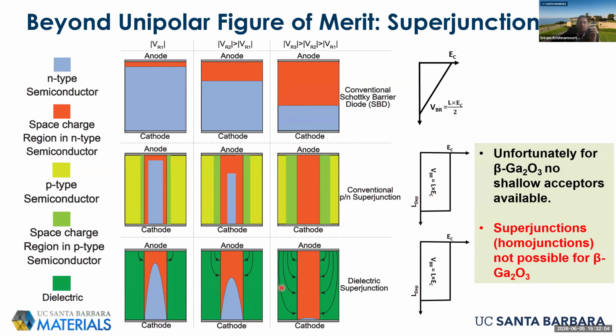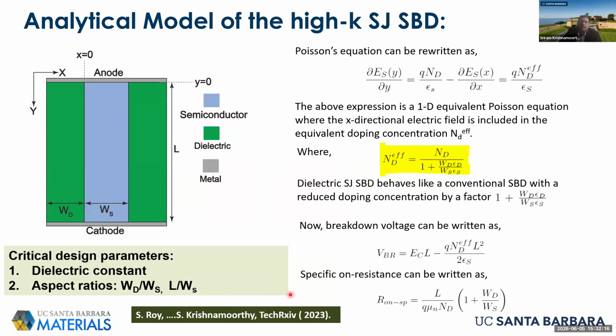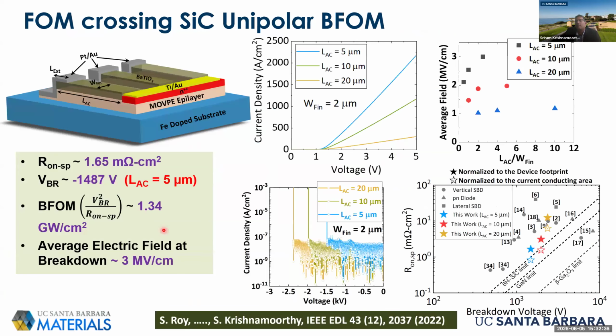have P-type material, right? So we were now thinking about ideas of using a dielectric and the fringing electric field within the dielectric to have a similar, superjunction-like effect in gallium oxide. And we tested out this idea in a lateral geometry first. We made some analytical models of this design, and you can effectively mimic a superjunction by carefully choosing the aspect ratio of a structure and the width of these dielectrics. If you carefully choose those values, then experimentally we've been able to show that you can get a very high figure of merit, which at this point in 2022 crossed the silicon carbide line with just 5 microns of anode to cathode distance in a lateral topology.